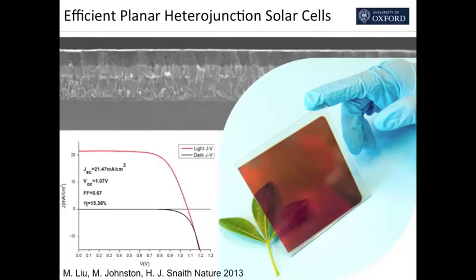So since then, we've discovered that we don't even need the insulating porous support. We can just make a thin film by a simple vapor deposition or solution processing, and these devices are now 15% efficiency, and our best devices are a little over 17% efficiency. So we've suddenly had a big step up, and if we look at the trajectory of this, here these are the perovskite cells in terms of efficiency.